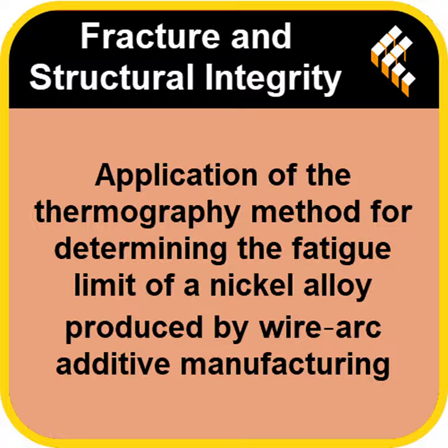And these results also lined up with other data for Inconel 625 made by other methods, right? Which is another good sanity check. It is. Those values are usually around 400 to 450 MPa, so this WAM material is performing right where it should be. And all this agreement really justifies using this Risitano IRT method for rapidly certifying these nickel-WAM alloys. It enables a huge reduction in the number of expensive specimens you need and, more importantly, the total test time.